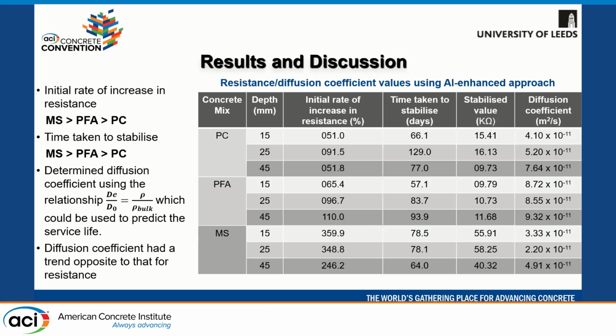Finally, this value of stabilized resistance was used to determine the diffusion coefficient using the relationship D_c by D_0 equals rho by rho bulk, which can be further used to predict the service life. The obtained diffusion coefficient value shows the opposite trend to that of the resistance.